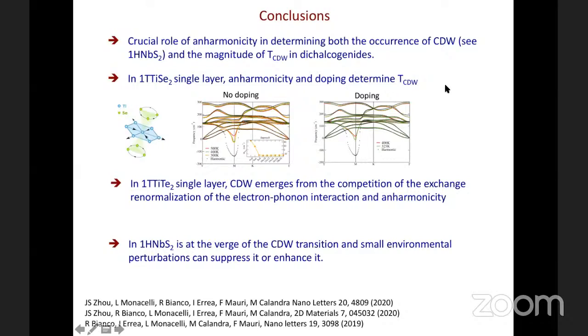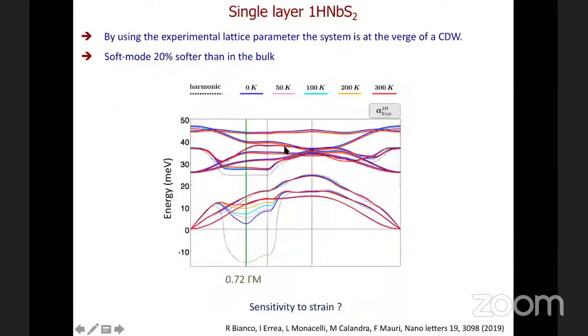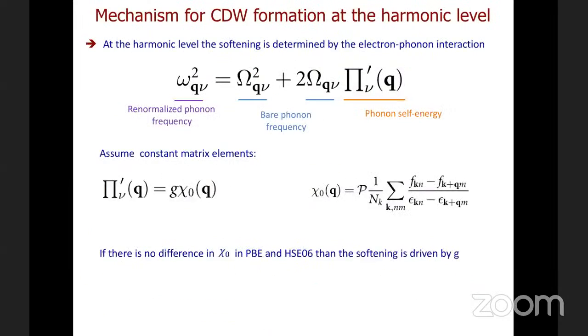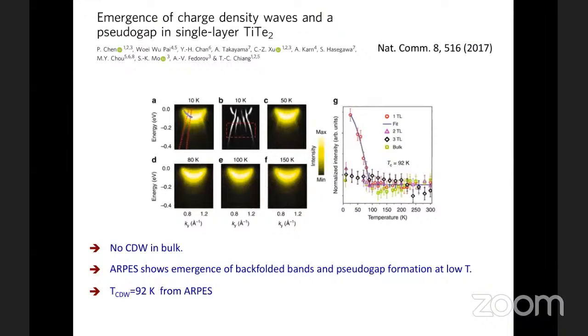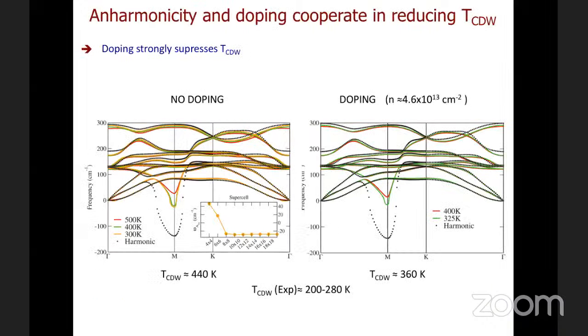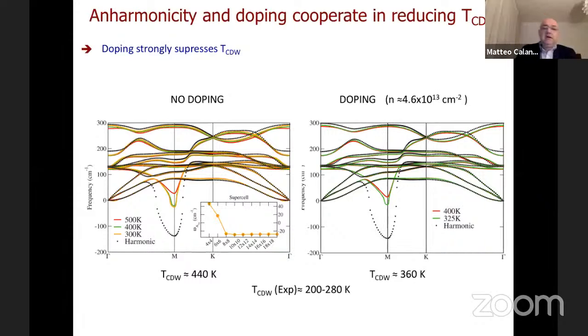I can start with a general question, Matteo. You mentioned in the beginning that charge density waves could also be driven by electronic correlations, but apparently, at least for the systems that you're considering, they are not playing an important role, or at least they are not needed to explain this. In these systems, the systems are probably not correlated enough to have a charge density wave driven only by electron-electron interaction, as it might happen in cuprates or also in one-dimensional materials like carbyne and so on.